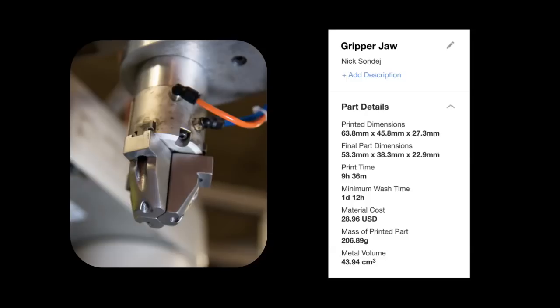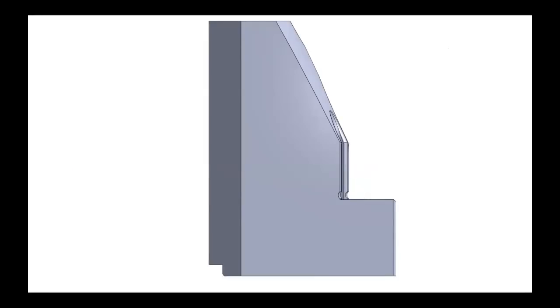So let's take a look at what this part will look like in CAD. This is the part in CAD, and if I were to simply wash this part in its current design, we might see something like this after 24 hours of washing. The green is representing the part being fully washed. You can see that in the middle of the part, it might not have been fully washed after 24 hours. So this is why it takes a day and a half roughly to wash this part. The reason is that there are no channels allowing the wash fluid to penetrate to the center of that part quickly. So it has to wash from the outside skin in.